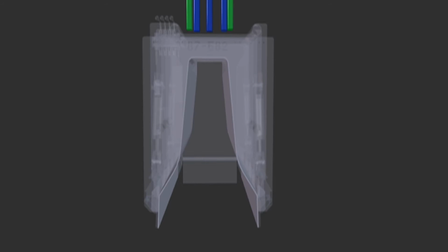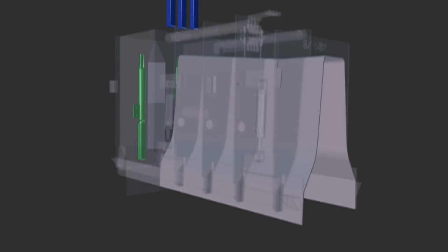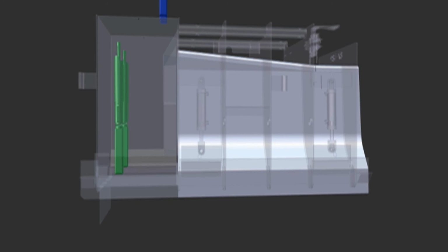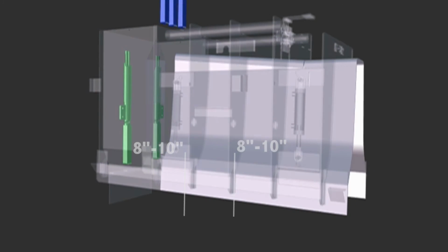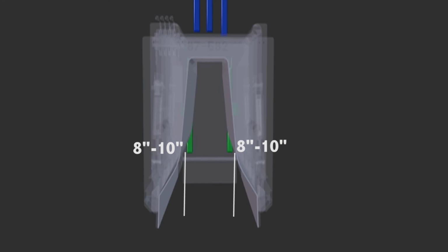Barrier and parapet molds are similar to header curb, just much larger. Two vibrators are mounted in the front side of the hopper. These vibrators are for compacting the base of the wall. They should be 8 to 10 inches from the ground and on either side.